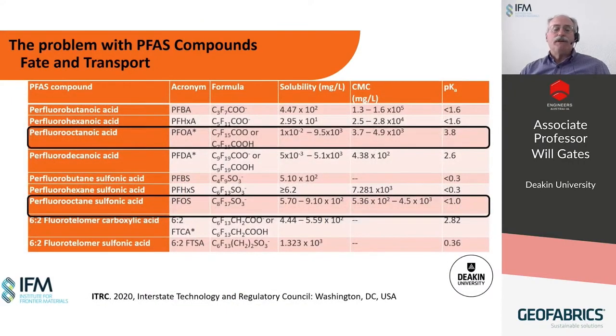So bringing this table back, which you've seen already, it's apparent that both PFOA and PFOS have similar water solubilities and similar critical micelle concentrations. But the big differences exist in their pKa, the acid dissociation constant. The pKa of PFOS is such that we can expect in most environments that PFAS will be in the anionic form, whereas we can expect many environments in which both the anionic form and the free acid form of PFOA exist simultaneously. These differences are what drive many of the interactions between PFAS compounds such as PFOA and PFOS with